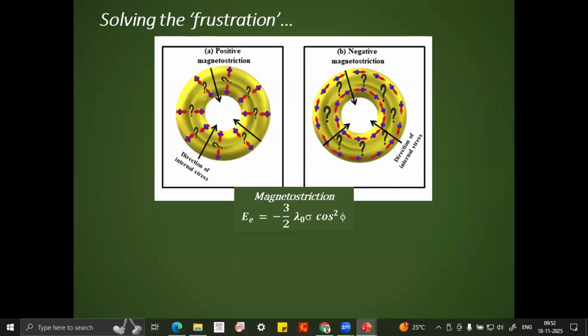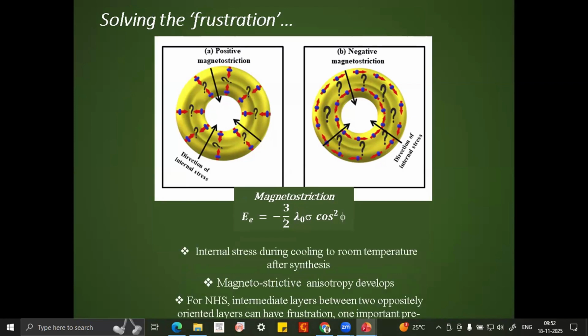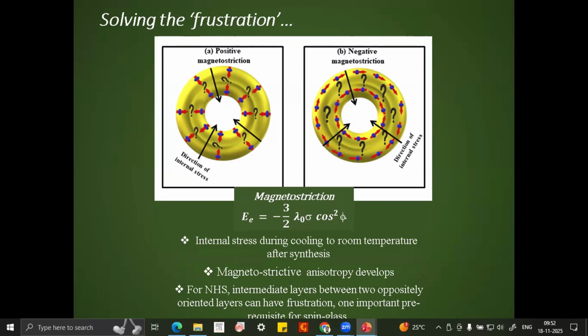What happens is that there is internal stress generated in the system. This internal stress is denoted by sigma, and lambda zero is the coefficient of magnetostriction. The same thing can happen for a positive magnetostriction sample and a negative magnetostriction sample. For a positive magnetostriction sample, lambda zero is positive. For the magnetostriction energy to be minimum, phi, the angle between the direction of stress and the direction of magnetization, should be either 0 or 180. So the magnetization direction can be along the direction of stress or opposite to the direction of the stress.